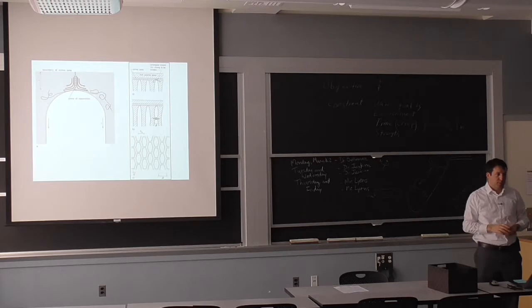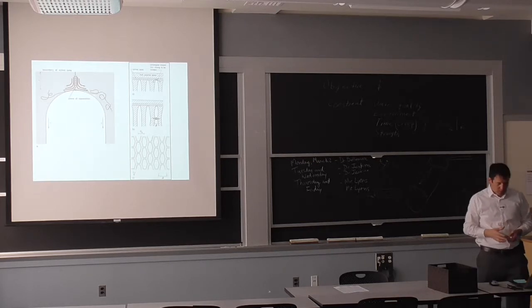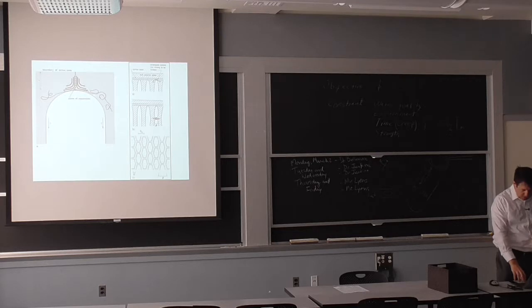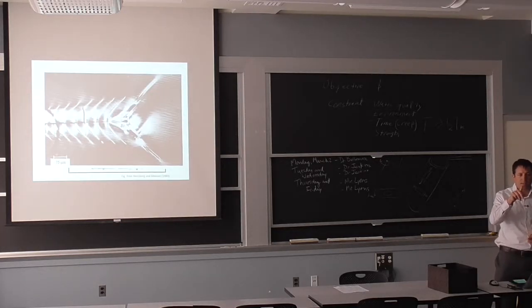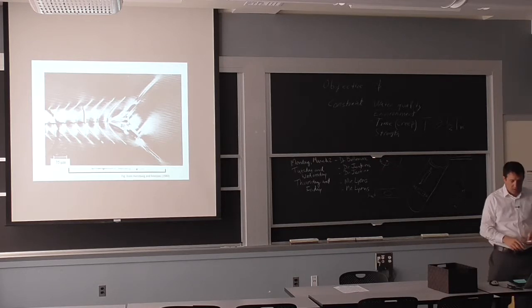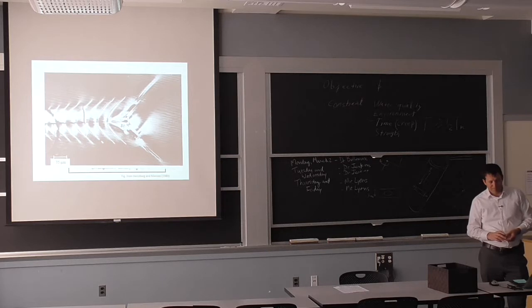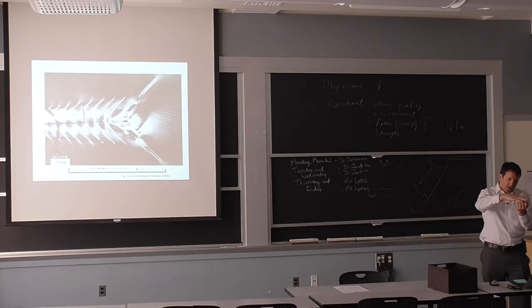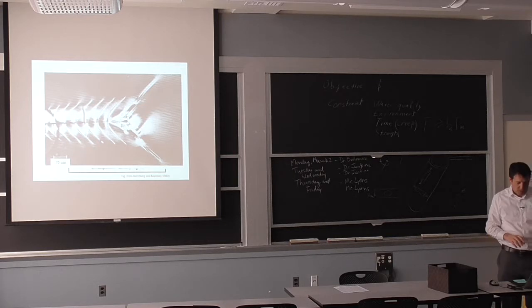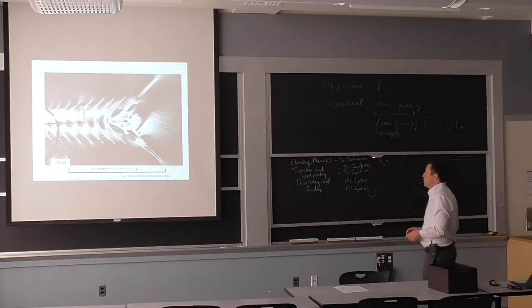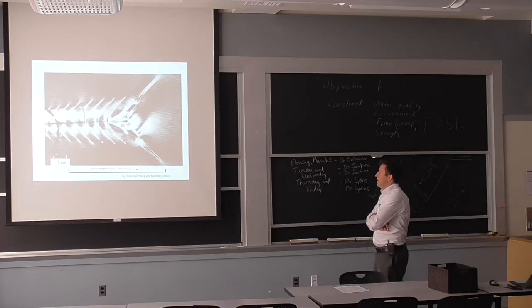I cross-tie them together. So this is a special case for thermoplastic. The example of the polycarbonate, the one I circulated where I said there's a little bit of surface waviness, is likely to be related to this other mode of localized deformation. Because what happens with the craze is instead of deforming through the entire material, you have a lot of strain over a very, very small thickness into the material. But you can have that here, what we call shear banding. It's not exactly as common.